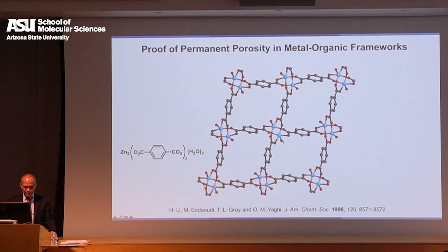And I had a postdoc come to me. His name is Muhammad Eddaoudi, while I was at ASU. This structure was made by Hailian Li. And then Muhammad Eddaoudi, as a postdoc, came to me. And I said to him, your job is to take this structure and see whether it's architecturally robust by measuring the gas adsorption isotherm, which is done at 77 Kelvin. And it is really the gold standard for proving that your material can remain open in the absence of guests. And therefore, you could use the pores.